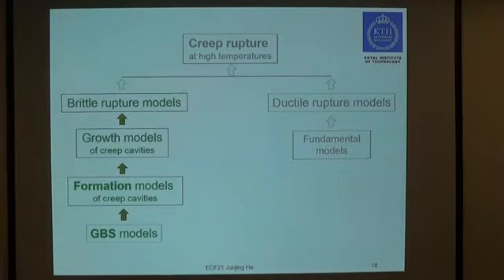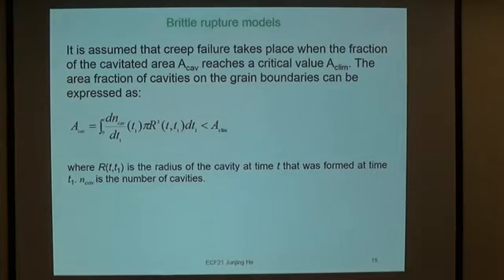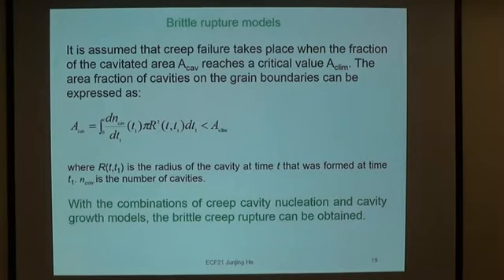Now with the nucleation and growth of creep cavity models, it's possible to predict the brittle creep rupture. It's assumed that creep failure takes place when the fraction of the cavitated area reaches a critical value, and the area fraction of cavities on the grain boundaries can be expressed as an integration of the cavity nucleation and the cavity growth. It's the cavity radius. So with the combination of creep cavity nucleation and the new cavity growth models, the brittle creep rupture can be obtained.